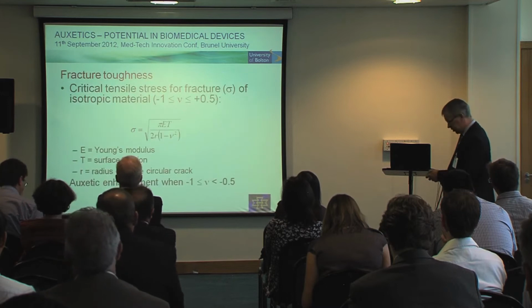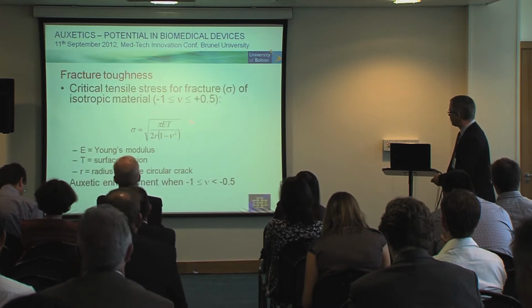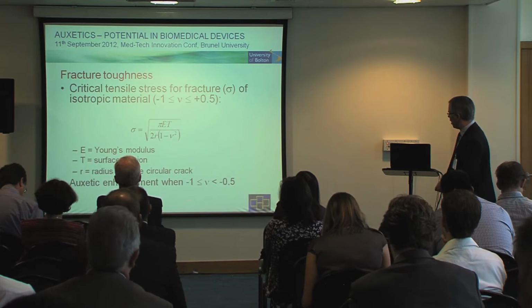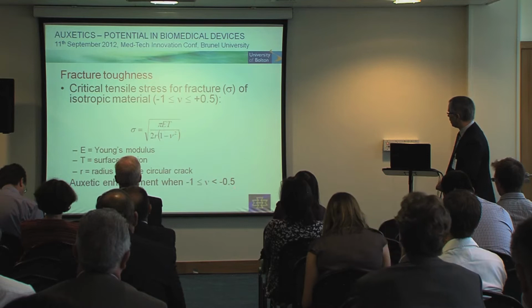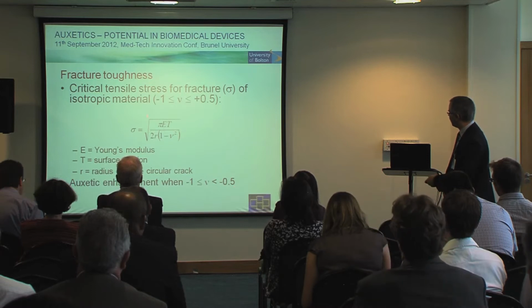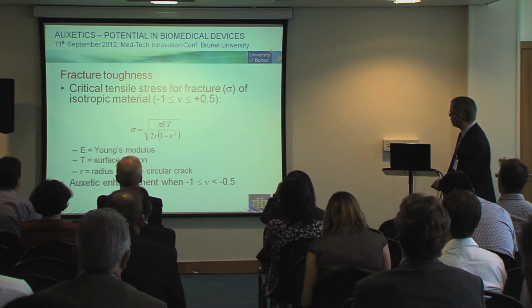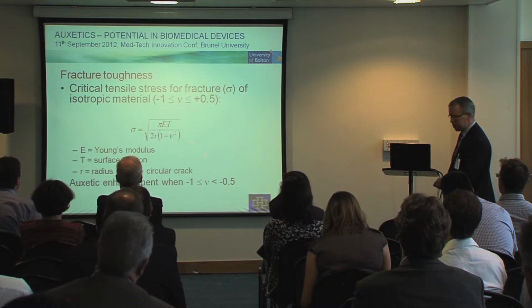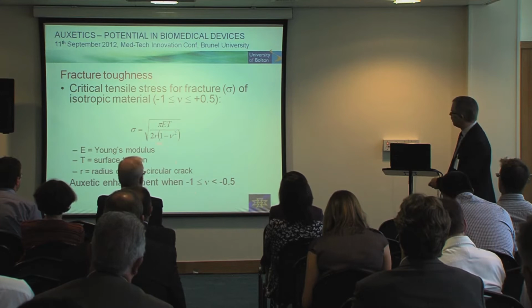Well, the fracture toughness is related to the Poisson's ratio by this expression, and Poisson's ratio for isotropic materials goes down to -1 and up to +0.5, not -0.5. Sorry, +0.5. That's the range of Poisson's ratio, and you can see for this expression, it's a Poisson's ratio squared term, so you get enhancements when you're in the -0.5 to -1 regime.